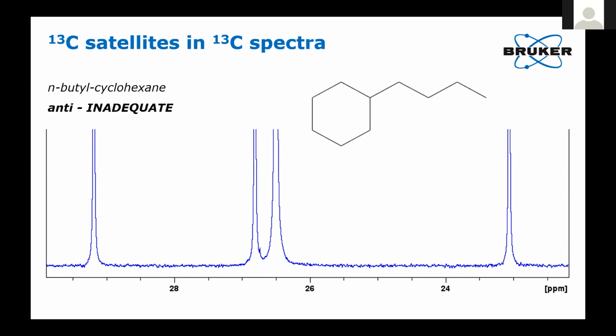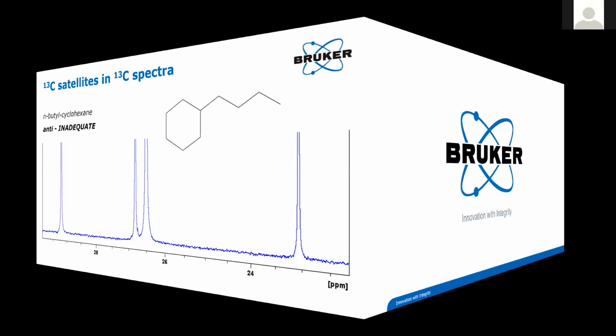With that, I end up with a carbon-decoupled carbon spectrum, or a spectrum where the neighborhood of the main signal is free of those carbon satellites, and I can see peaks which are really close to those fairly large peaks.